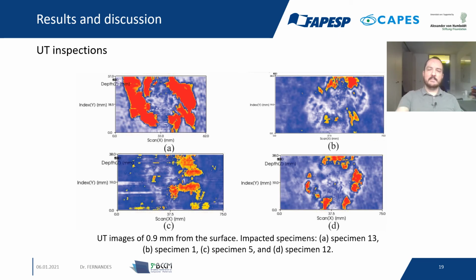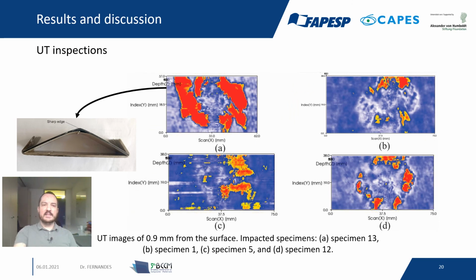Here in this A, we have a specimen that was not subject to thermal shock cycles, 0 thermal shock cycles, and when it was impacted, it created a sharp edge here. So because of that, as you remember, in the ultrasonic inspection the transducer is moved with a robotic arm, and there was no contact around the edges. So that's why we have these very pronounced red areas here. It does not mean that there is a defect there.